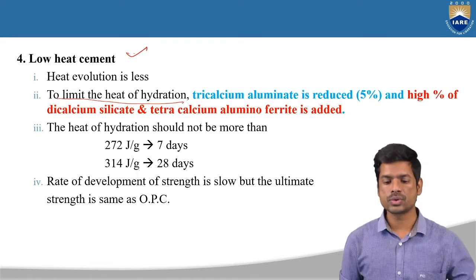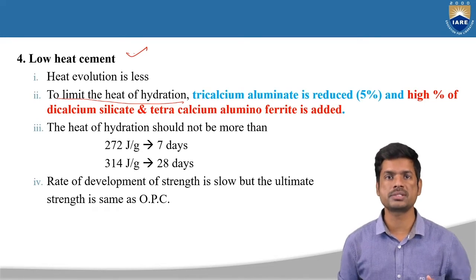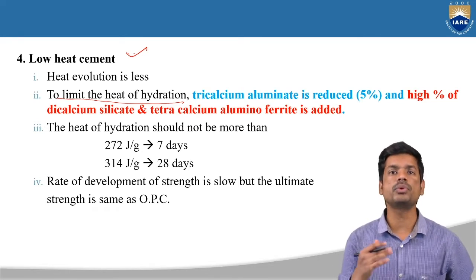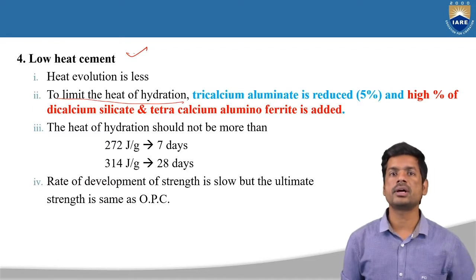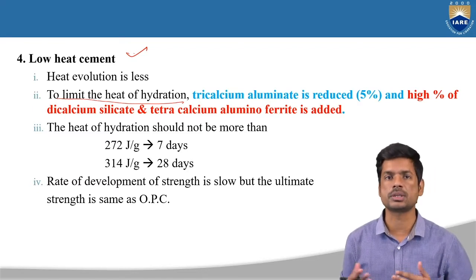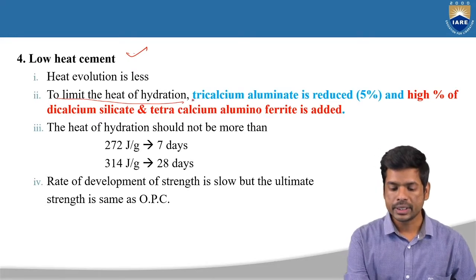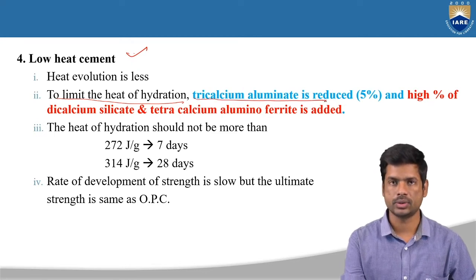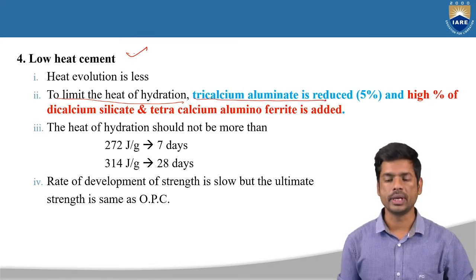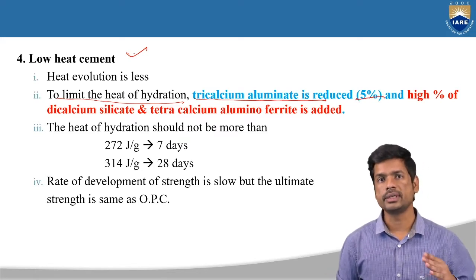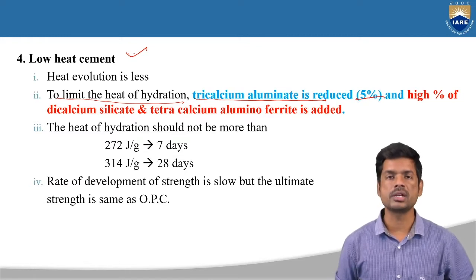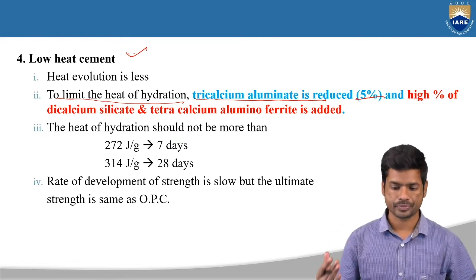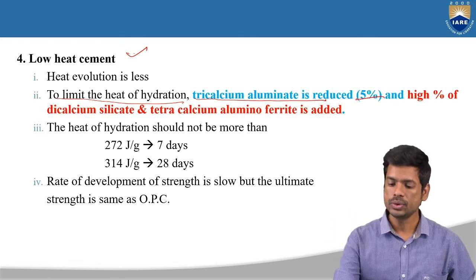So what is going to affect the less heat here? Okay, by decreasing some amount of chemicals, or by changing the chemical composition of cement, we are going to produce this particular low heat cement, right? So here, we are going to reduce the tricalcium aluminate up to 5%. Normally, in normal OPC cement, the percentage of tricalcium aluminate is around 6 to 11%. But here we are going to reduce that particular tricalcium aluminate to 5%.